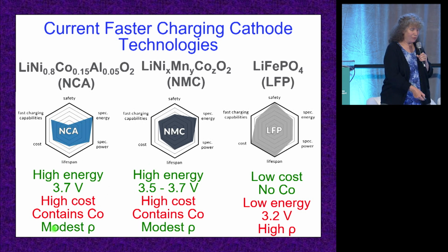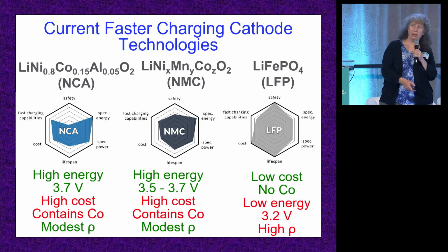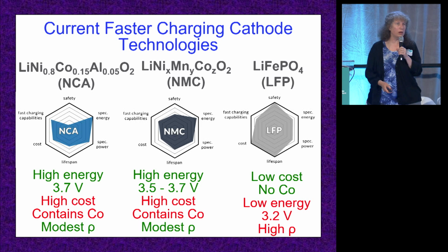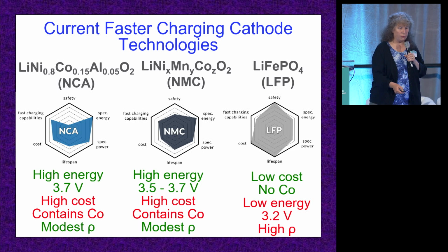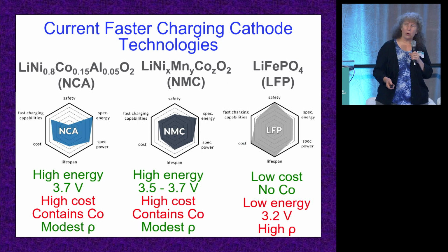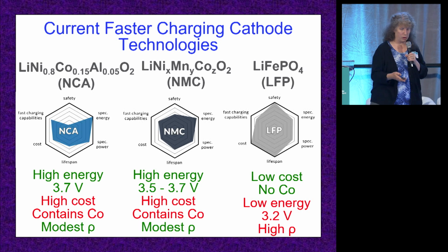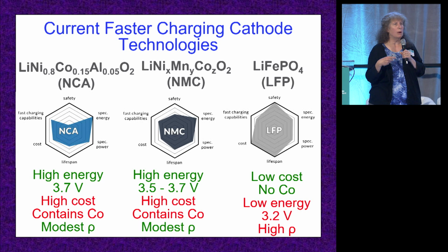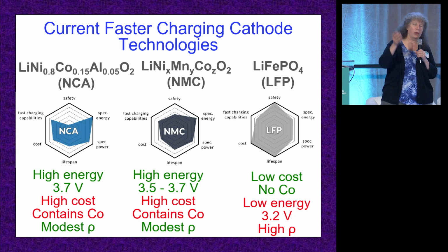They have low resistance. That makes them pretty easy to charge fast, but they contain cobalt and they're really expensive. And they're the reason that electric vehicles are so expensive. A lot of low-cost vehicles from China are currently using lithium iron phosphate. This has no cobalt. It's a much lower energy material, a much cheaper material, but it is a much lower voltage material, only 3 volts, and that means it is a much lower total energy stored material. It also has horribly poor resistance, and so you have to coat the whole thing with carbon.